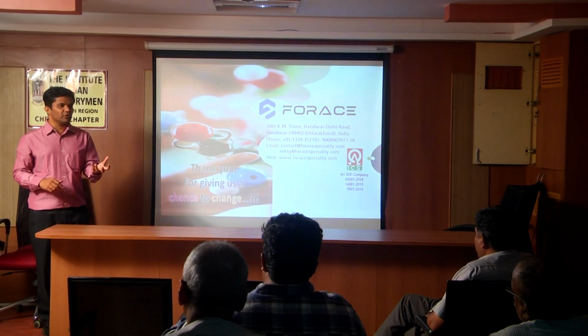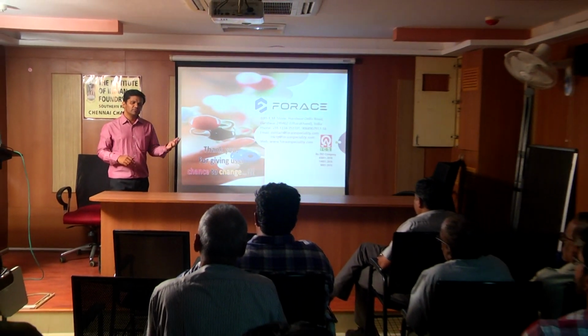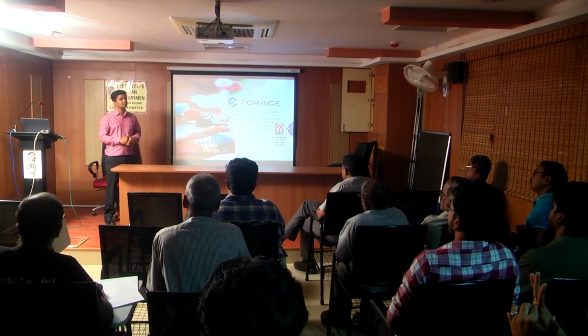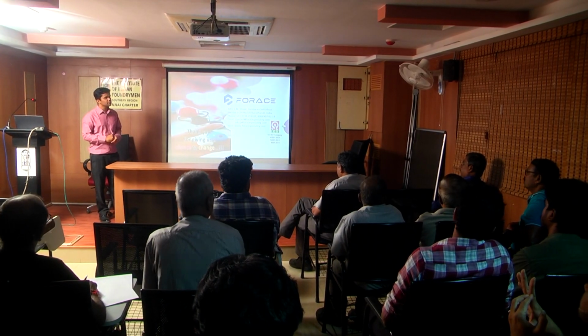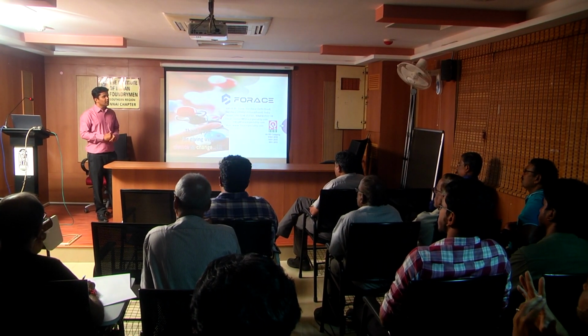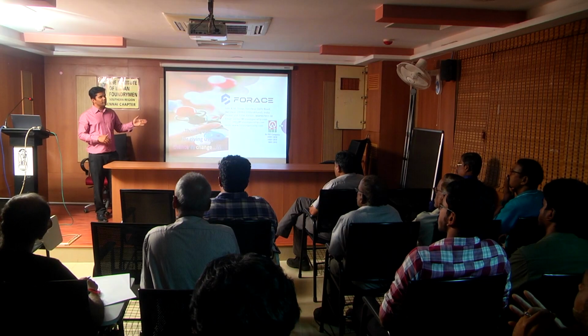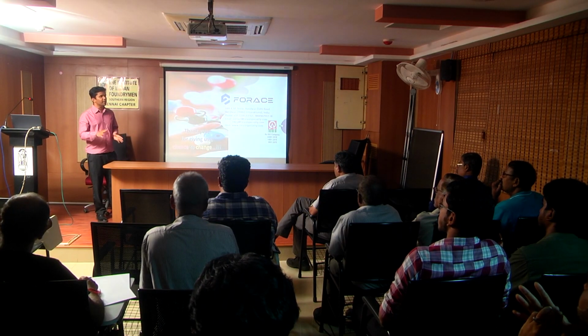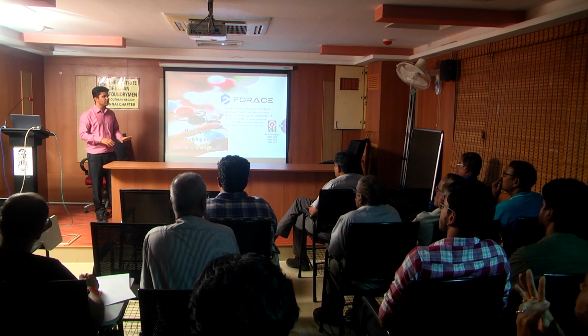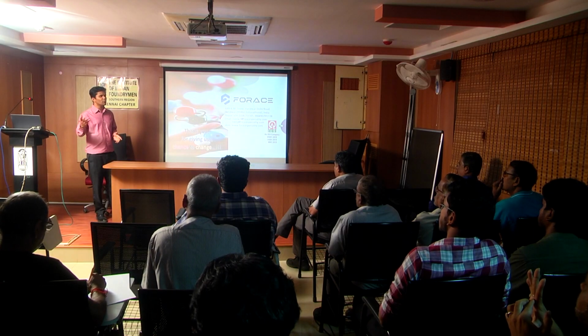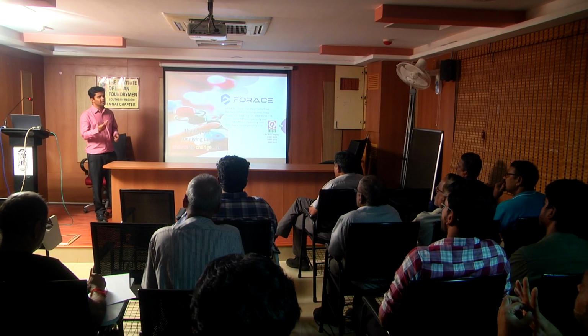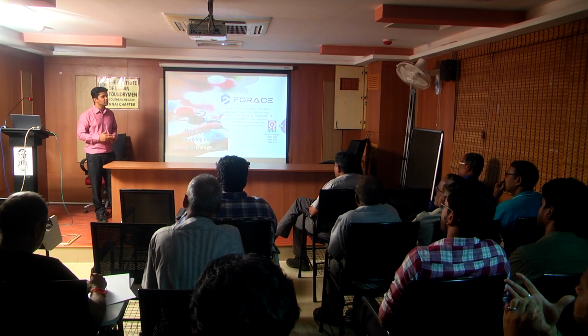Exothermic reaction will happen because of the alumina percentage. It will increase the temperature. What is the composition of the sleeve generally? Generally, it starts from 15% to 27 or 28% in exothermic sleeves. In high density sleeves, it is more than 30-35%, or it can go up to 40% also.